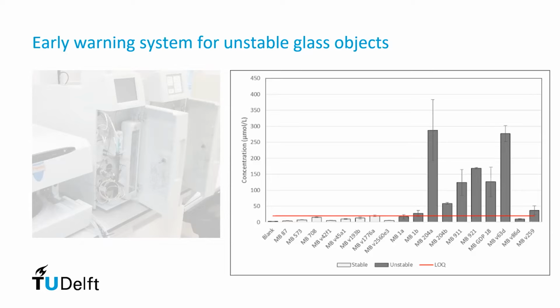And this slide just demonstrates that we went to the Museum Boijmans van Beuningen, where they had just done a large collection survey, and they identified glasses which they considered stable and unstable, and cleaned them all at the same time. So we had a baseline level of the condition and appearance of the object. And after a certain amount of time, we started analyzing those sample deposits using ion chromatography, of which you see a faint image here on the left.